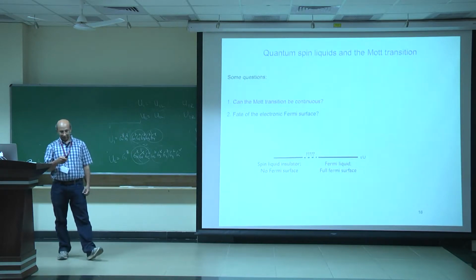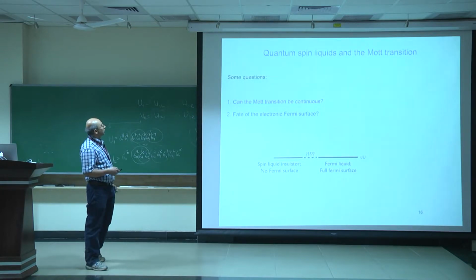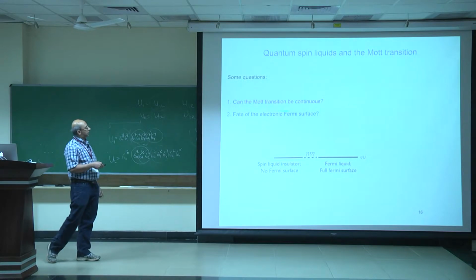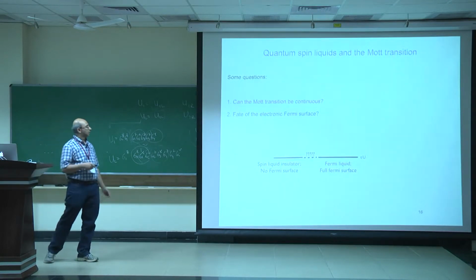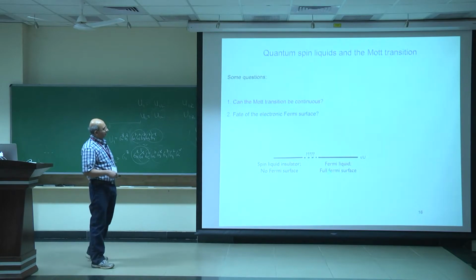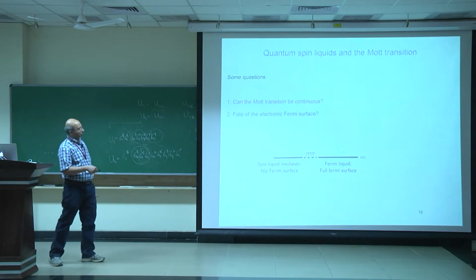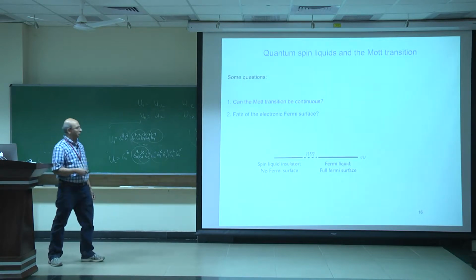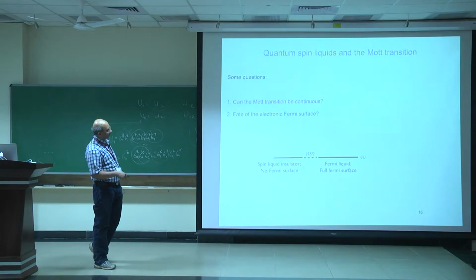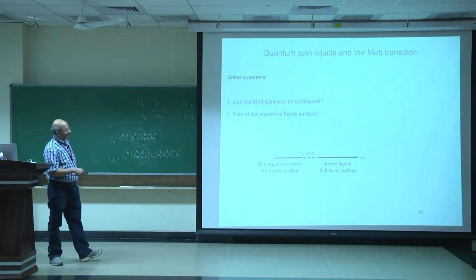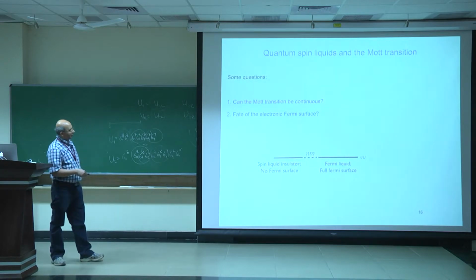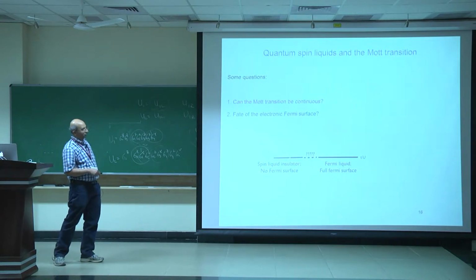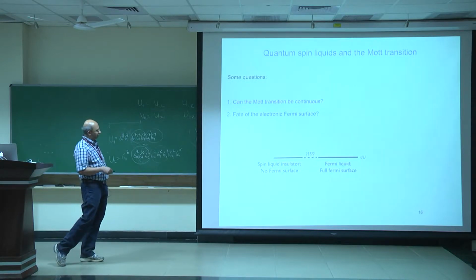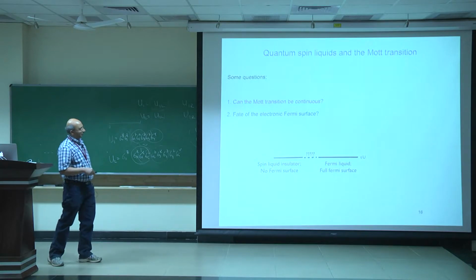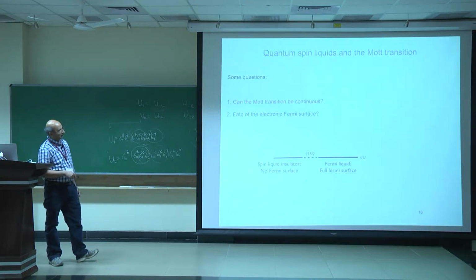Okay, so let's think about the possibility of a Mott transition to a quantum spin liquid from a Fermi liquid. Some fundamental questions are: can the Mott transition be continuous? What happens to the electronic Fermi surface? So again, returning to this phase diagram, as a function of T over U, let's say on the triangular lattice, as is appropriate for the organics, at large T over U we have a Fermi liquid state with a full Fermi surface. At intermediate T over U, when the system has just become a Mott insulator on the triangular lattice, there's actually a lot of evidence, both from experiments and theory, that you go into a spin liquid Mott insulator. But any insulator, whether it's a spin liquid or not, has no electronic Fermi surface. So something needs to happen to the Fermi surface along the way.